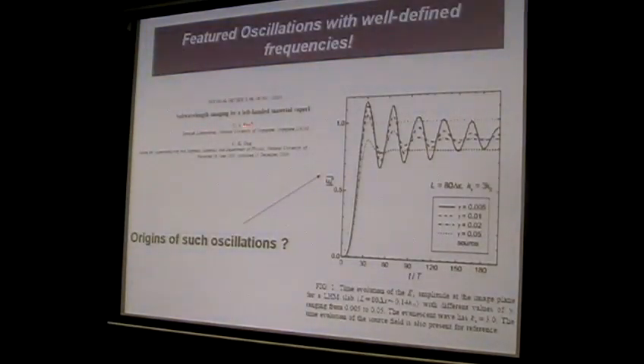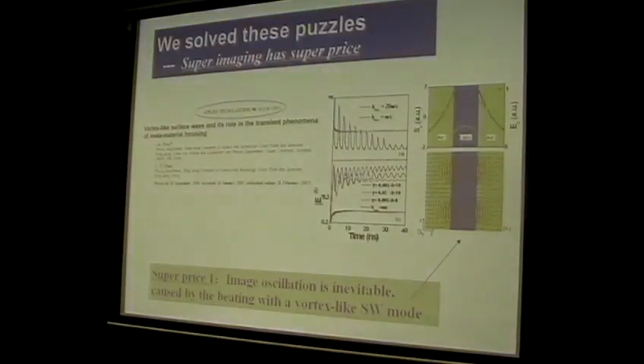And several years later, a group in Singapore reported that this oscillation is actually a very characteristic oscillation with a very well-defined frequency. This reports the image as a function of frequency, as a function of time, and they found this beating phenomenon. So the question arises, what's the origin of this oscillation? CT and I, when I was still in Hong Kong, did a study to solve this puzzle.